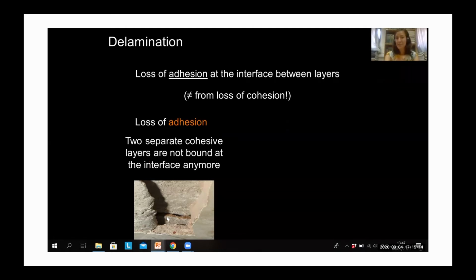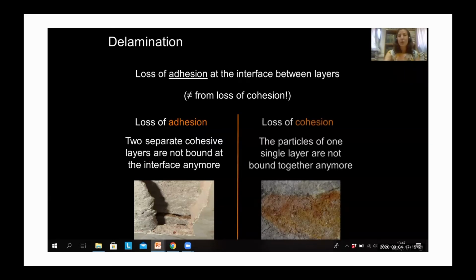However, as you can see here, there is a loss of adhesion, meaning that there is a little gap at the interface. On the other hand, loss of cohesion means that the particles of one single layer are not bound together anymore. And so you have, for example, here, a powdery paint layer or a powdery plaster, a powdery surface. So we're going to talk about adhesion today.